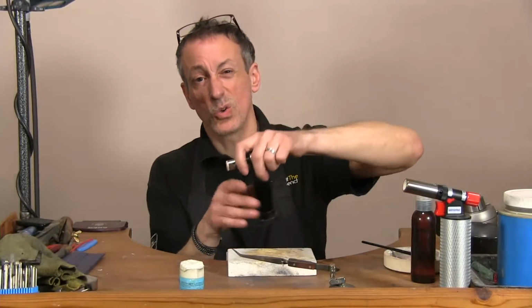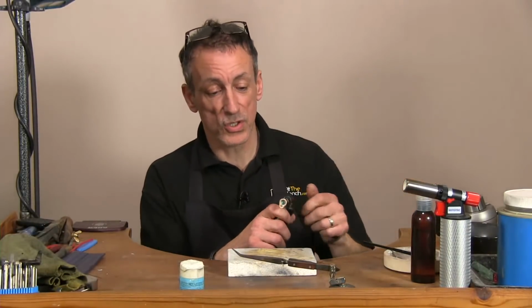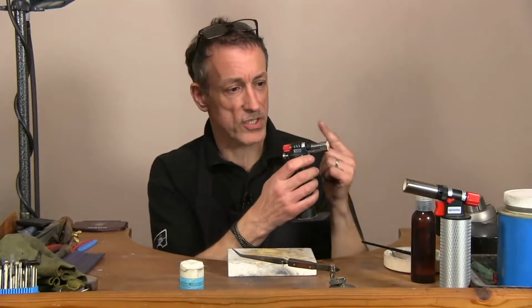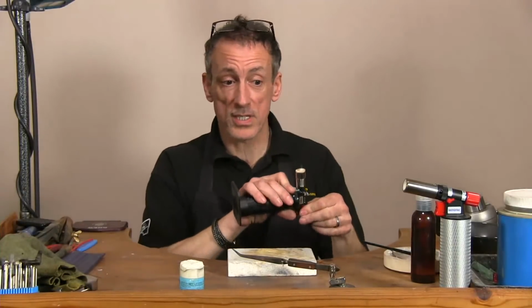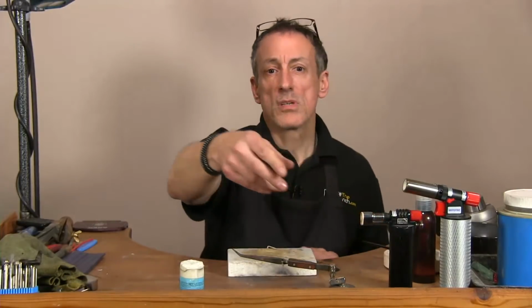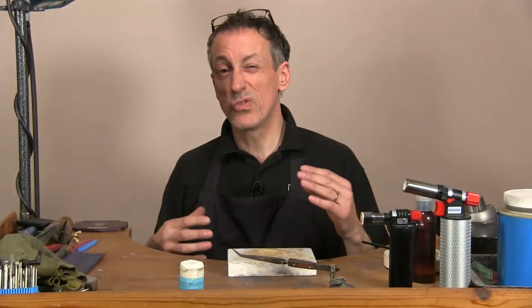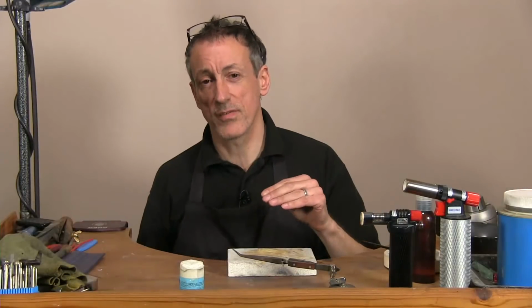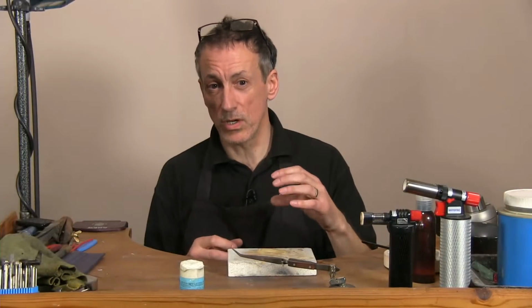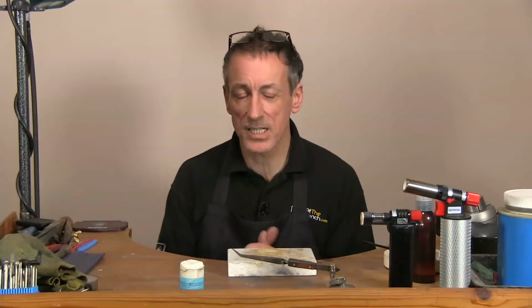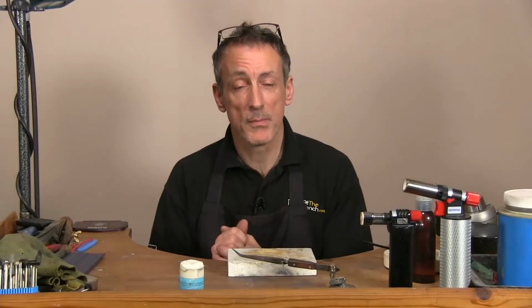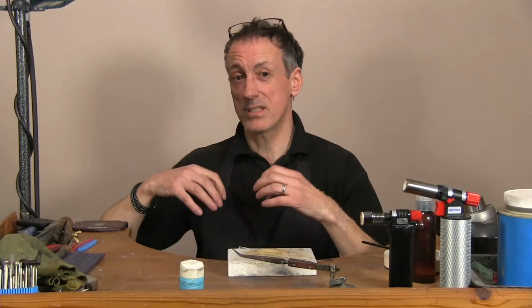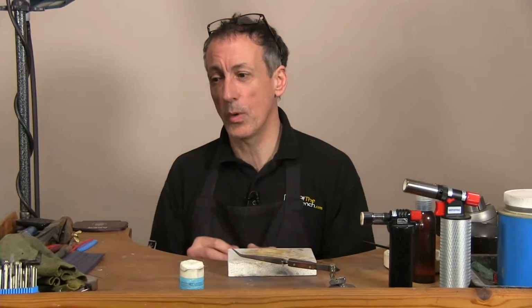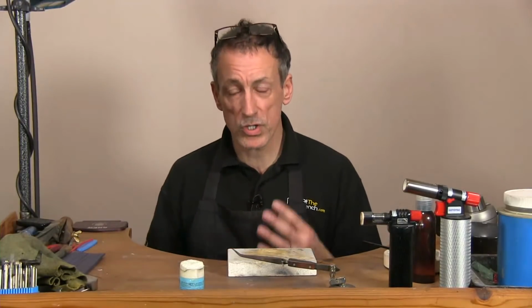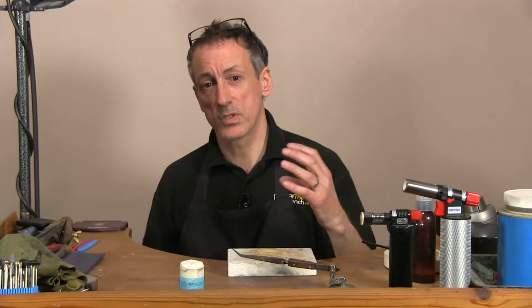This is the reason why these torches are pretty good, because you just have this flame and nothing else. You can't add any more oxygen to it. So when you come to melt silver down, don't have a really strong, hissy, oxidizing flame, because the silver will absorb the oxygen. And I wouldn't really melt silver many times, because if there's oxygen going into the silver, the oxygen will oxidize with the copper. So don't be in a rush really to melt your silver. The silver is going to absorb it.